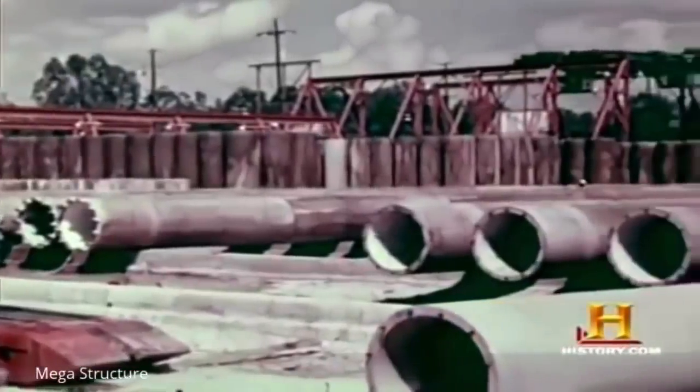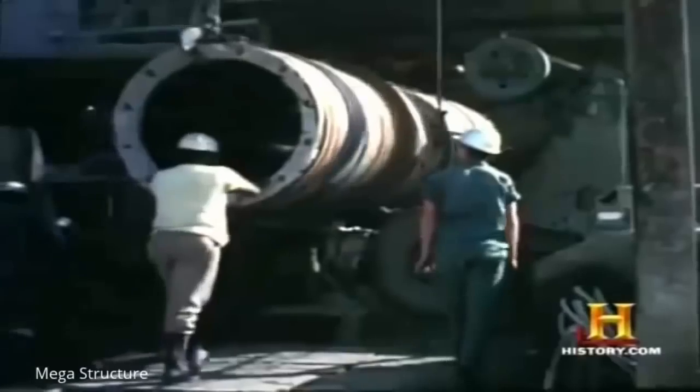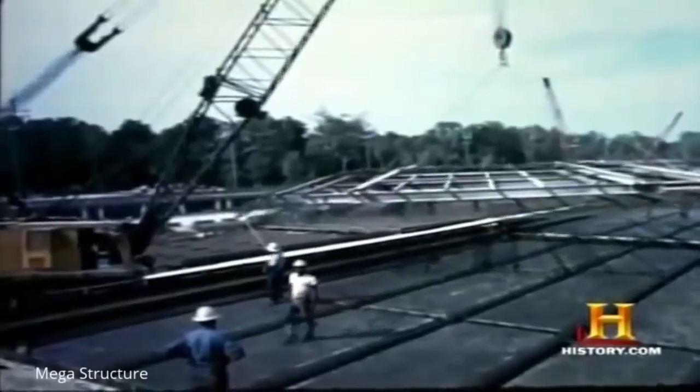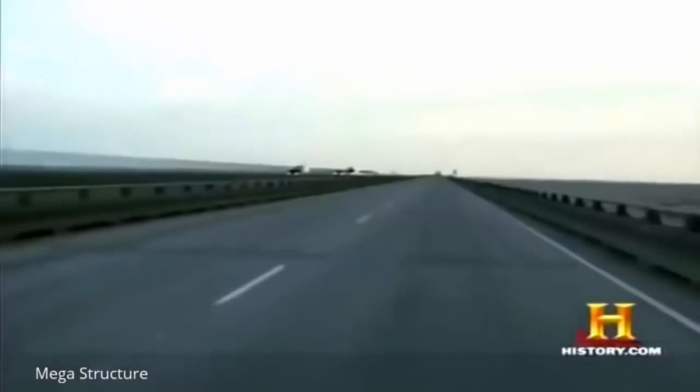The new pilings were manufactured with a slightly improved, thicker 5-inch wall over those in the first bridge. They used a little thicker wall to get a little more cover over the reinforcing bars so that they had better resistance against salt attacking the reinforcing bars. The quality of the steel and the concrete had advanced in the decade between the first and second bridge construction.